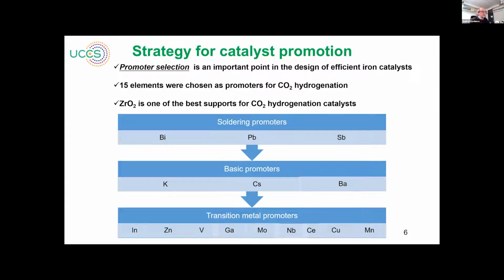So of course, we have to choose the promoters. Promoters are chosen on the basis of the literature and our scientific intuition. We tested a lot of promoters. In this work, we tested 15 elements as promoters for CO2 hydrogenation, but in total about 30 catalysts, because some catalysts have been promoted with 2 elements.